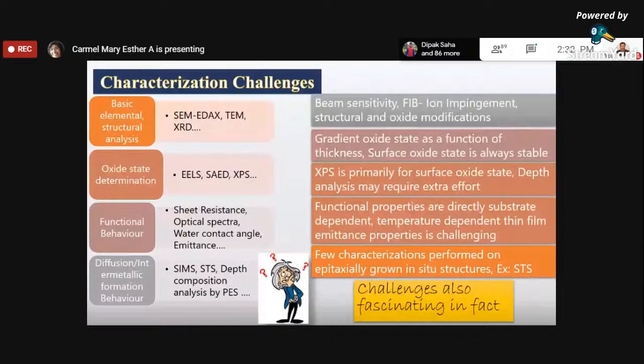The first major problem is beam sensitivity. When we prepare the sample by FIB or some other method and expose it to SEM and even TEM, we are always facing beam sensitivity. The next is that we observed the developed layer is not uniform throughout the thickness. It may always show gradient oxide states. The surface oxide state is always stable, so when we try to see the surface oxide state, we cannot determine that it is the overall thin film oxide state. So this is also one important challenge. XPS is normally used for surface oxide state, but when we try to use XPS for depth analysis, it requires a lot of expertise in that field.